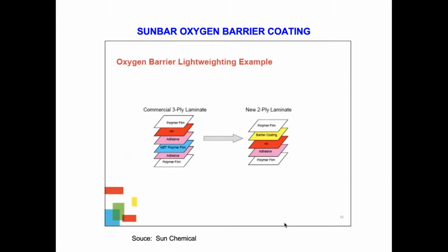Here's an example of lightweighting where we're going from a kind of generic commercial 3-ply laminate there with a metallic or metal layer barrier in the middle to a barrier coating, which allows us to take this down to a 2-ply laminate, make it much simpler.